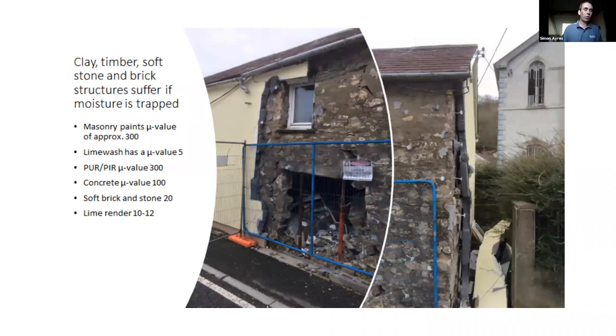So why that's important is because when we get it wrong, when we use products like cement and other materials like that on traditional buildings to renovate them, or on new buildings which are being made out of the same sort of materials, you can end up with catastrophic results. Moisture trapped, so using materials that don't allow moisture out, can mean that moisture accumulates in the structure. Timbers rot, natural fibers rot, and you end up with things basically falling down, or you end up with an unpleasant internal environment.